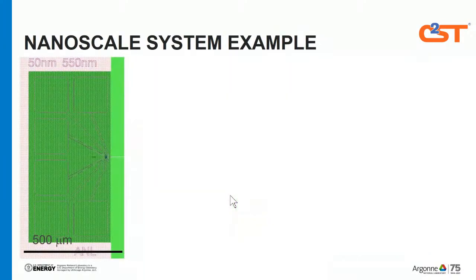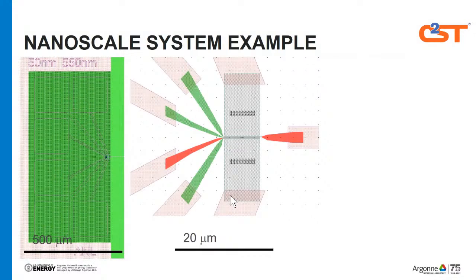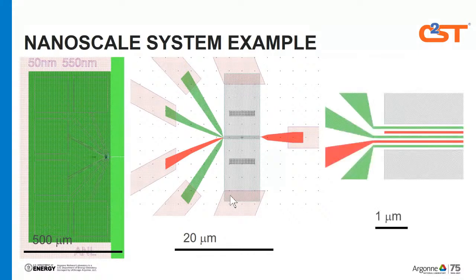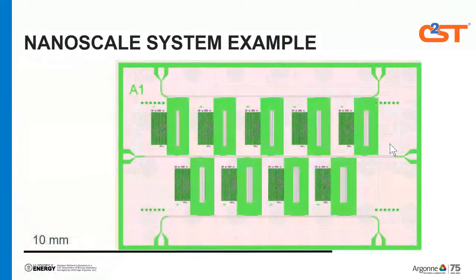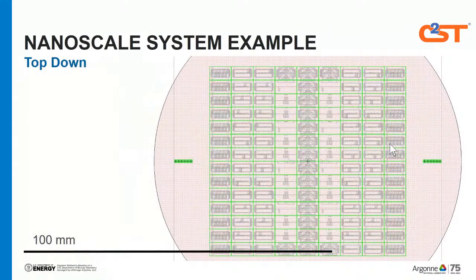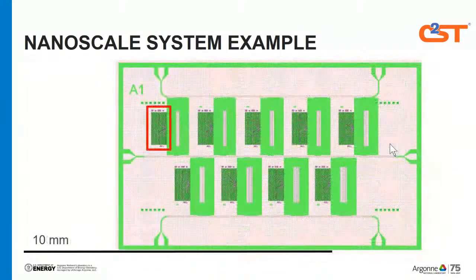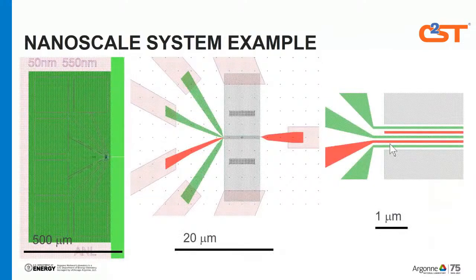We zoom in even further. Now we're down to about half a millimeter. Then we zoom in even more, and we're down to 20 micrometers. And now if we zoom in even more, we can see that each one of these bars is 50 nanometers. We're going to make this into a metal pattern so that we can control the electrical response of a carbon nanotube across a gap. So you can see as we go back up, we started out at a macro scale, 4 inches, 100 millimeters, and then we go all the way down to the nanoscale, but we have to keep zooming in so that we can see what we're doing.